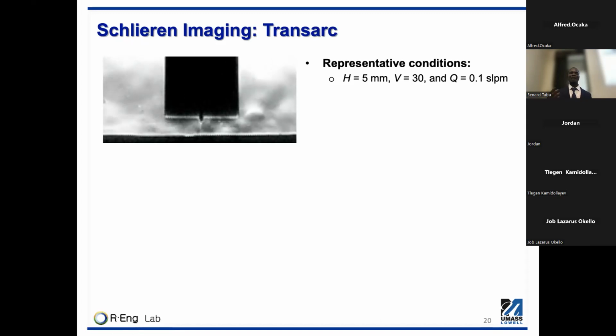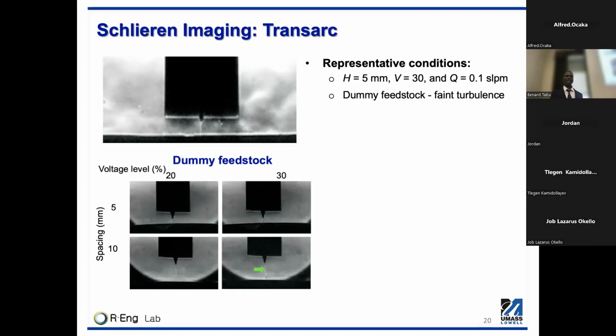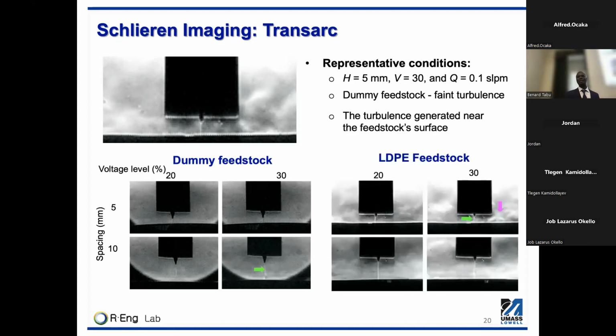And we wanted to see if we can get a qualitative description of the correlation of this with the hydrogen produced. What we did was we took a dummy feedstock of glass quartz, and when we subject it to the experimental conditions, we see that yes, the plasma is faintly visible and the turbulence is formed, but it's not really very pronounced. So when you look at the one for the feedstock, the turbulence is actually more pronounced, and it's even higher for a higher voltage level and shorter spacing, and that's the condition where we had the highest yield of hydrogen. So we concluded that yes, the turbulence is correlated to the production of hydrogen, the higher the degree of turbulence.